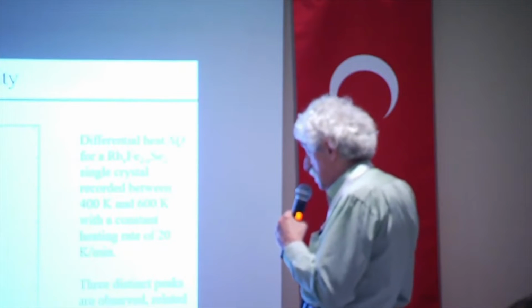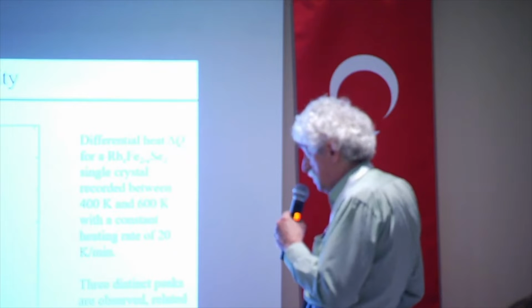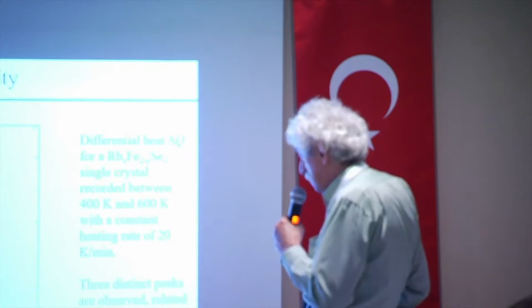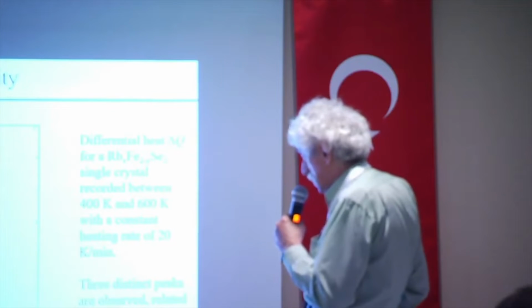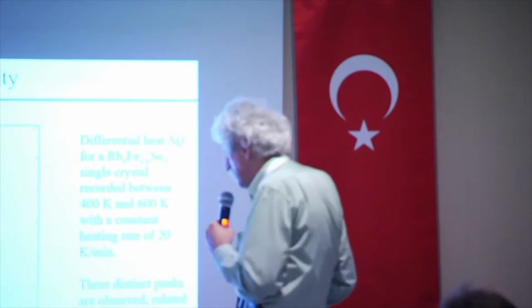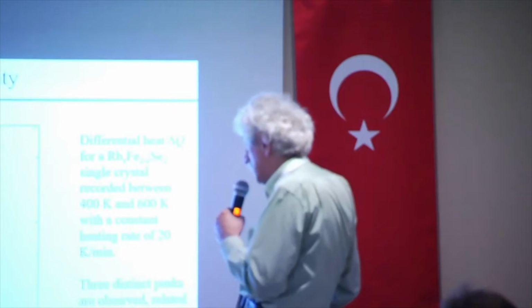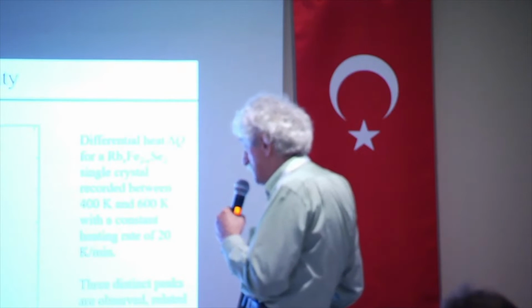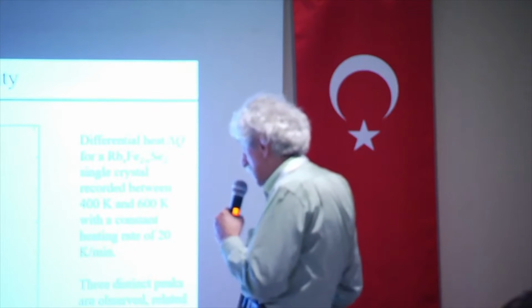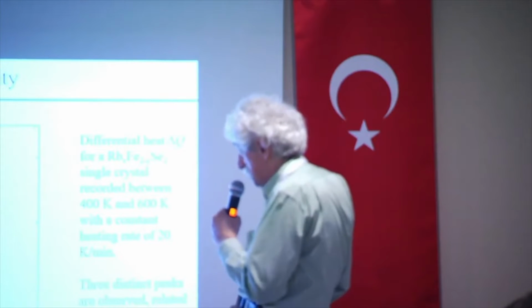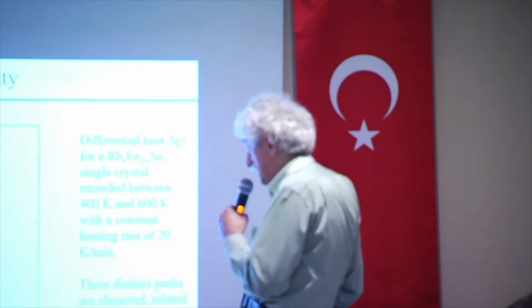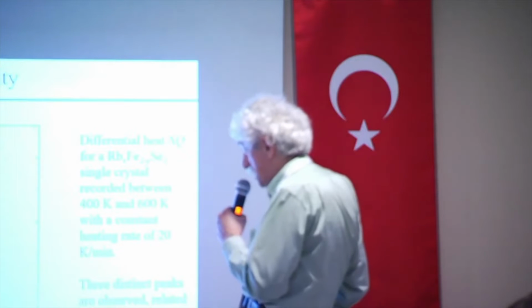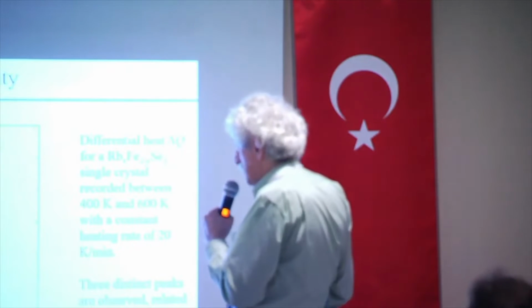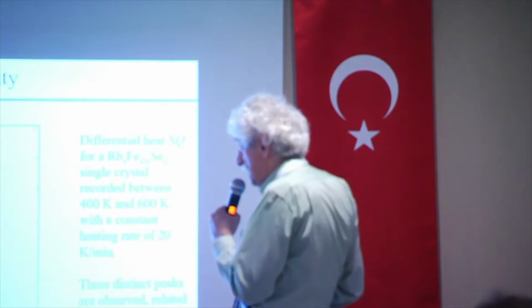And if you perform a measurement of the temperature dependence of the heat capacity of this material, you will find that there are basically three transitions. This is a phase separation transition. This is a structural transition here. So at this temperature, the structure which is responsible for superconductivity appears. Here there is a Néel temperature, but here is a phase transition temperature. And in this region there is only one phase, but the two phases appear